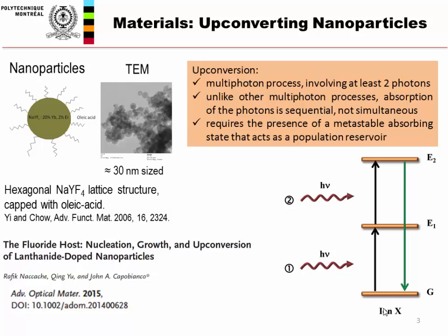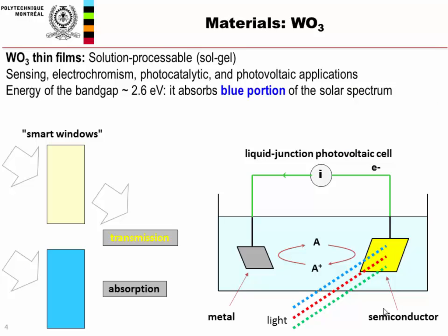We have in our case a sodium yttrium fluoride host. It's a very specific host, and it has been selected because of the limited phonon effect in the matrix, and so in view of maximized efficiency of the emission. And we deal with, here it's written 30, it's actually 45 nanometer, the size of the nanoparticles we use. So, this is one of the materials, one of the partners, these upconverting nanoparticles.